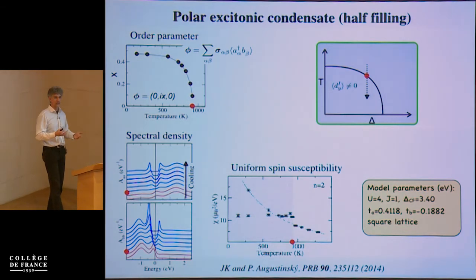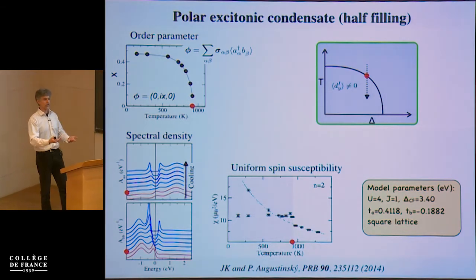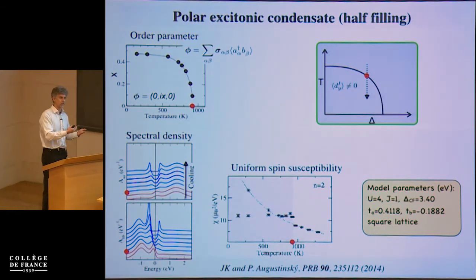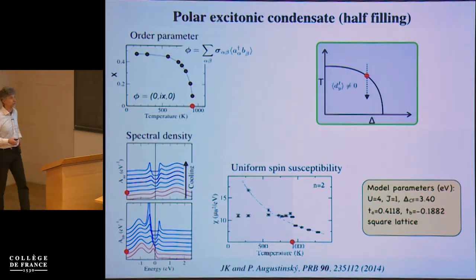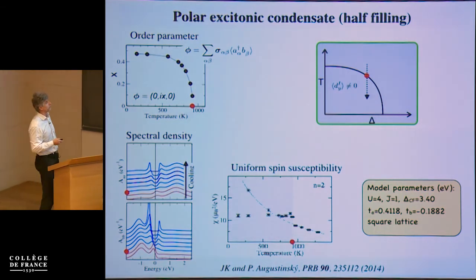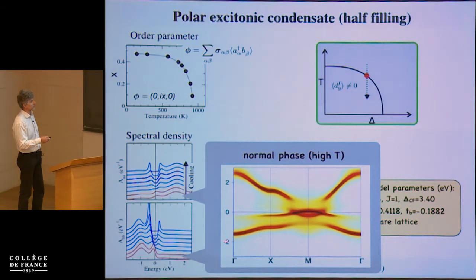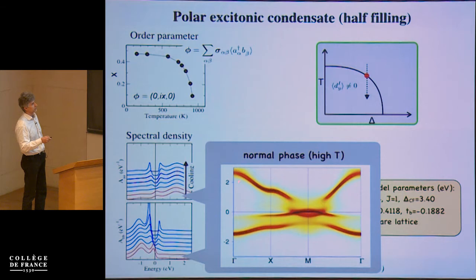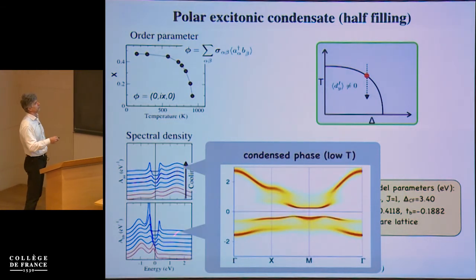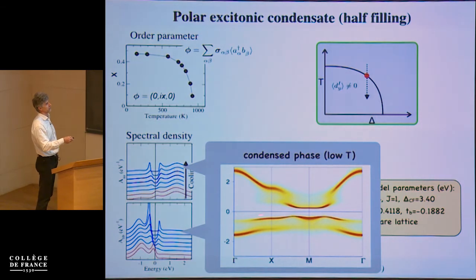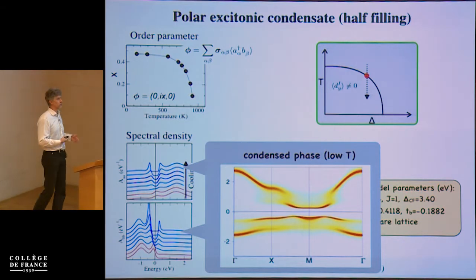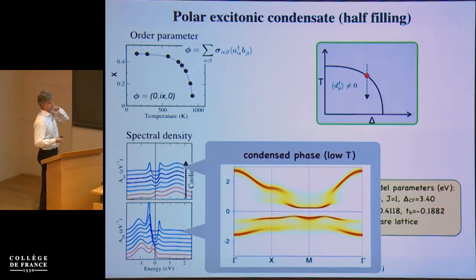So on the 1-particle level, they can be mapped onto each other. If you look at the response to the electromagnetic field, there is of course a huge difference, because here we have excitons which are neutral, while in a superconductor we have Cooper pairs which are charged. So this is the same picture in k-resolved fashion. Here you see the 2 almost touching, or touching, bands, and if we go to the ordered phase, we see this excitonic gap opening here. So indeed we get what Mott called an excitonic insulator.